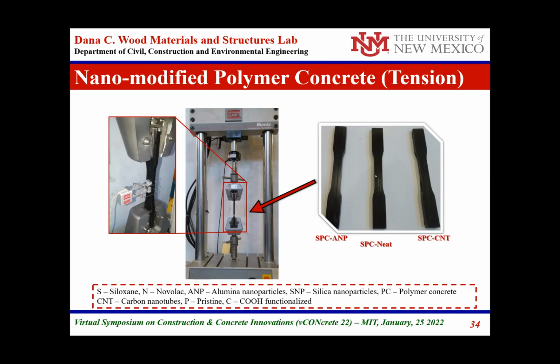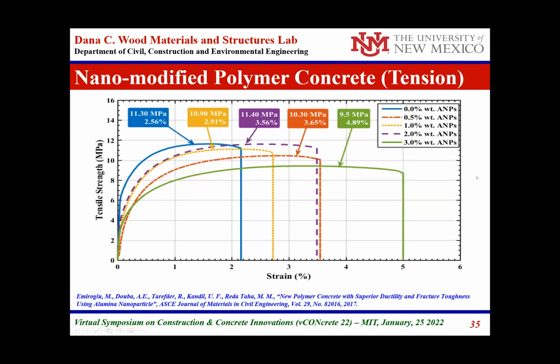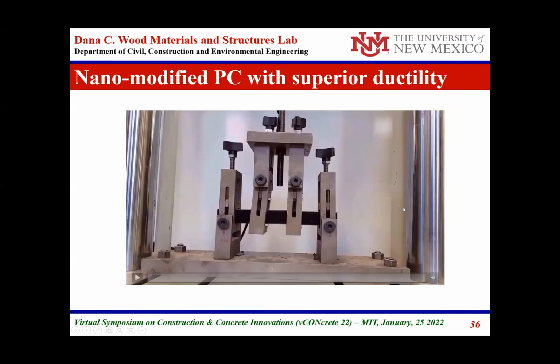This is an example of a tension test of this concrete. You can see the significant improvement in tensile strength and strain ductility. So the same strength almost, but the ductility is much higher. It's about 10 megapascal in strength, but significant improvement in ductility with the use of alumina nanoparticles in the range between 0.5 to 1 and 2%.